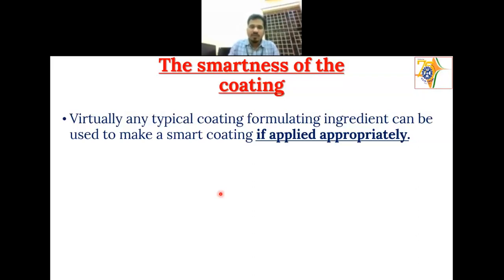Maybe if you add more than 5-8% of graphene or some other novel additive, the other properties of the coating will be affected. So we need to keep these things in mind, because the most important thing of a coating is that it should act as a barrier. When the coating fails to act as a barrier, then whatever smartness you are adding to the coating is of no use. So that is the most important. Whatever you are adding should not affect the barrier property of the matrix.